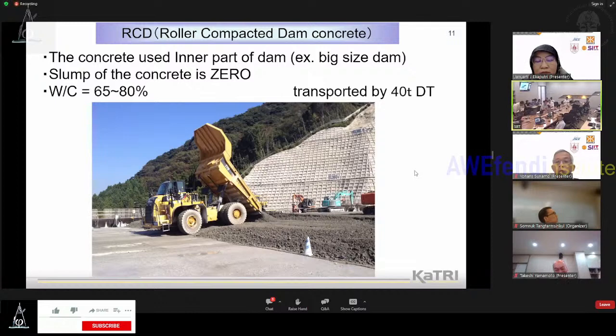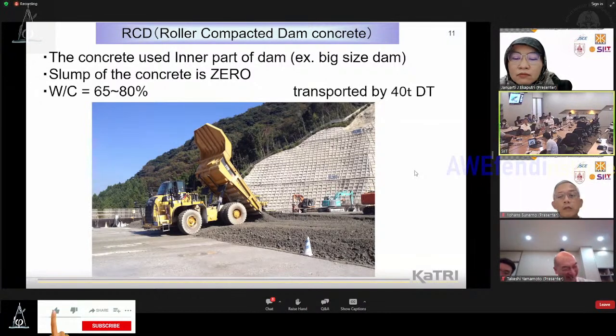For example, for big dams, RCD, roller compacted dam concrete, is also used in Japan. When the height of the dam is over 50 meters, we use RCD concrete as the internal part of the dam concrete. The slump of the concrete is 0, and it is very hard. The water cement ratio, the water binder ratio, is almost 65 to 80%, and the unit weight of binder is almost 120 per cubic meter. So the dam RCD concrete is very hard.